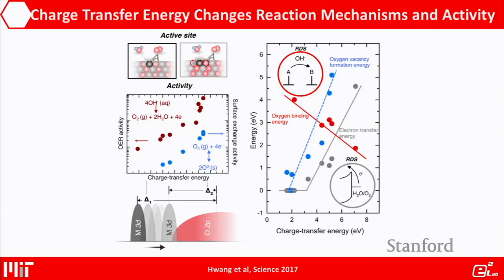More importantly, we can correlate the charge transfer energy with the energy barriers for different processes. And we understand why there is a correlation: why, when we reduce the charge transfer energy and make the compound more covalent, OER activity increases. The essence is that initially we are reducing the charge transfer barrier, and up to a certain point there is no electron charge transfer barrier. Then we're limited by deprotonation from the oxide surface during the oxygen evolution reaction. We change from an electron transfer limited process to a deprotonation limited process.